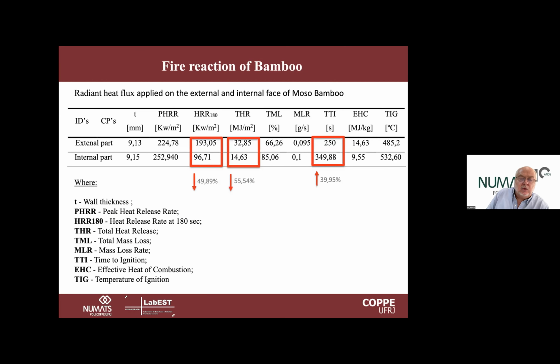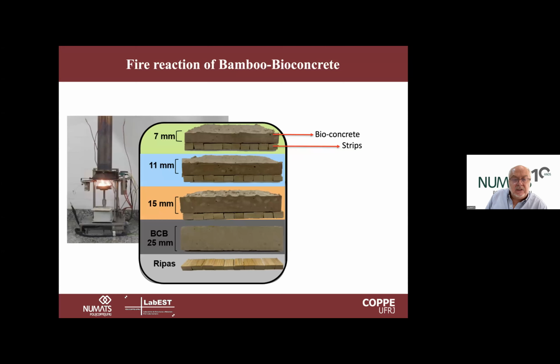So from these materials we also get many properties from this test, but the most important I put here, it's the heat release rate. This is very important. So if the material releases heat very fast, the time to ignite is low. So we should, of course, protect this material with a layer of some fire retardant. In our case, as this bamboo is going to be used inside bioconcrete, we did a study to see the effect of the covering layer of the strips, to see the minimum covering we need to have to protect the system.